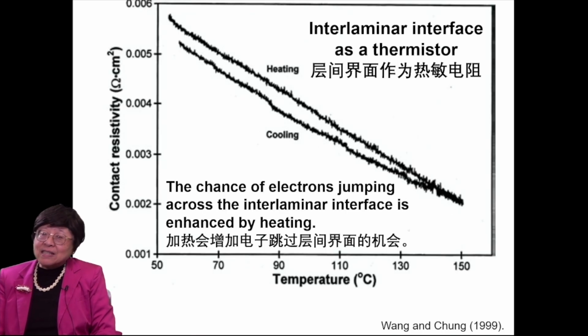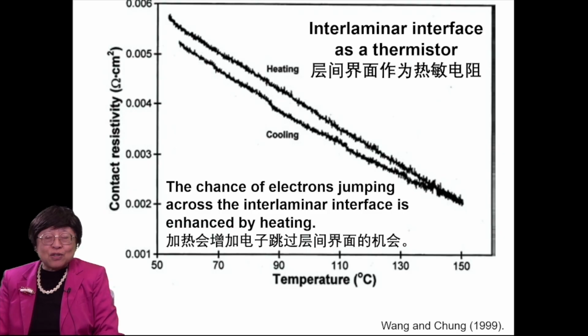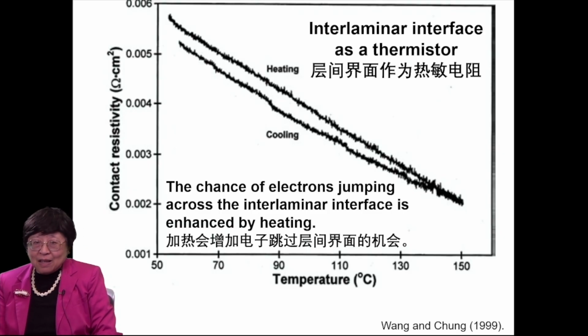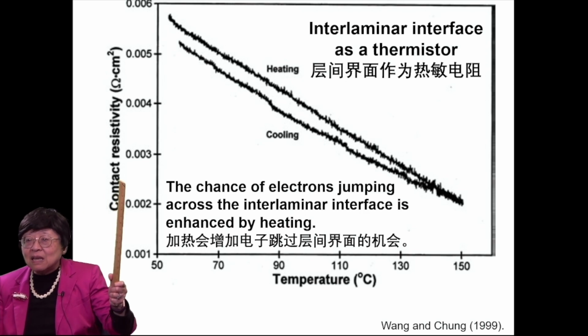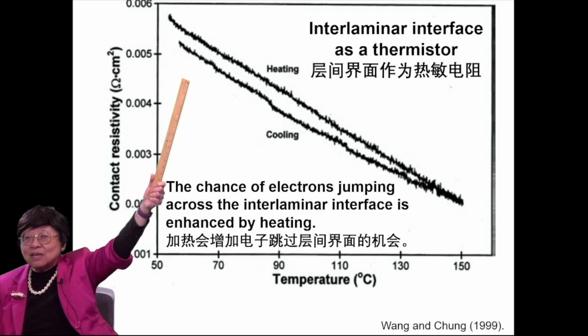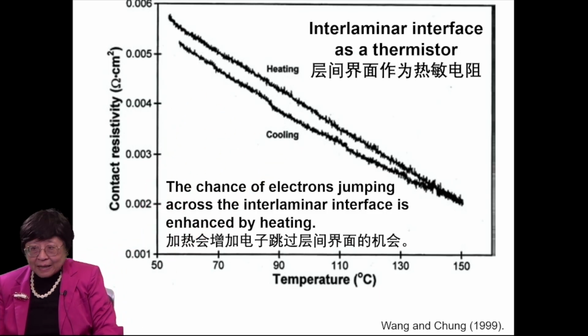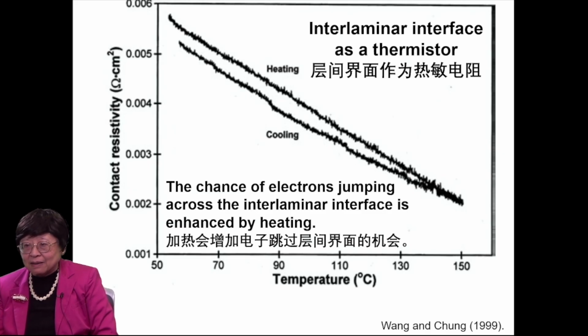The interlaminar interface can also be used as a temperature sensor, that is a thermistor, which refers to a temperature sensor based on resistance measurement. And this is the contact resistivity versus temperature, and it decreases upon heating. And that is because the chance of electrons jumping across that interface is enhanced by the heating, thus promoting the through-thickness conduction and therefore decreasing the contact resistivity upon heating.